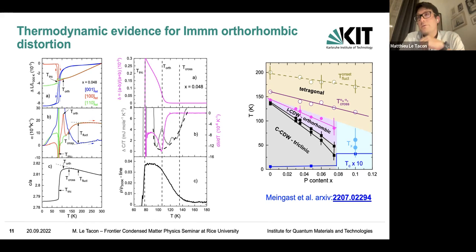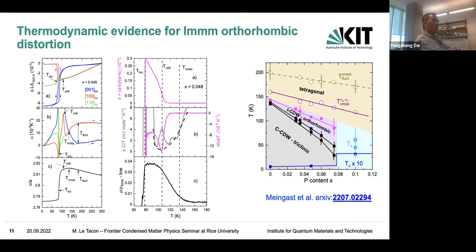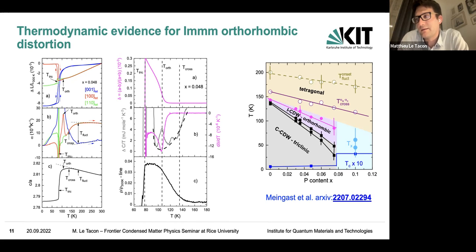If you look at the original paper by Alaska Subedi and David Singh, where they did the first-principles calculation for that system back in 2008, they calculated the electron-phonon coupling, and they just found a Tc of 4 Kelvin. Of course, there's always this uncertainty about mu star and everything, but it's the right order of magnitude. So the highest Tc that you get so far in the system is not really far from what you expect from the McMillan approach, electron-lattice coupling.